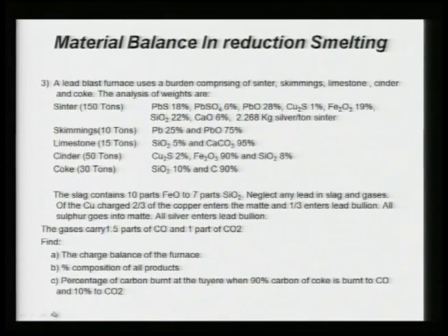Now, it is further said the conditions of the slag and the components are given to some extent. It is said the slag contains 10 parts FeO, 7 parts SiO2. It is also said you neglect lead in slag and gases. Further conditions are imposed on the copper in the charge: 2/3 enters into matte and 1/3 into lead bullion.